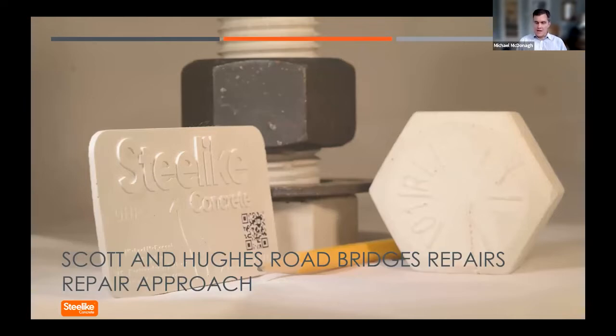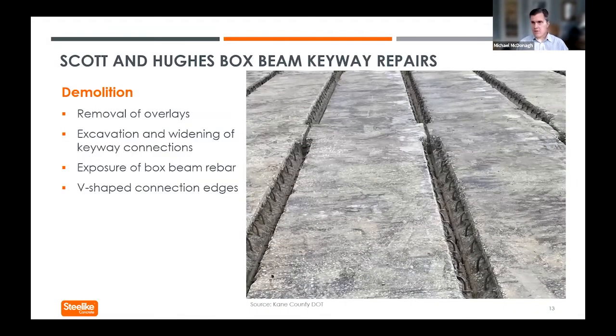So the Kane County Department of Transportation, to repair the two box beam bridges, Scott and Hughes Road, opted to use ultra high performance concrete. And their approach was to first remove the overlays and then excavate and widen the keyways so that the rebar inside the box beams was exposed. And also creating sort of a V shape, to the best of the contractor's ability, within those widened keyways. And of course, you can see in the photo here, the keyway widening being complete.